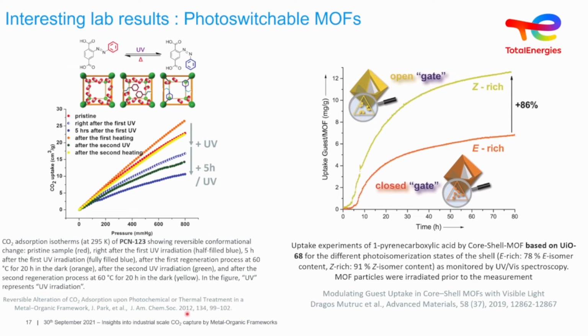This is some work carried out almost 10 years ago where they looked at the effect of UV, and after 5 hours of UV, the people suggested that we could have different conformations of the linker here, and the linker could be more or less open to have more or less space for the CO2.